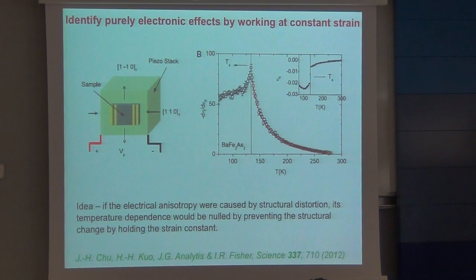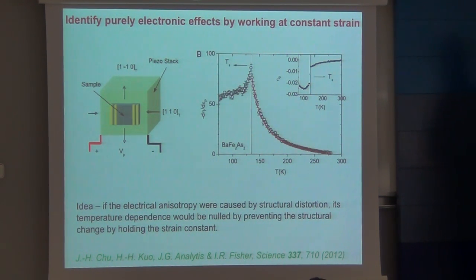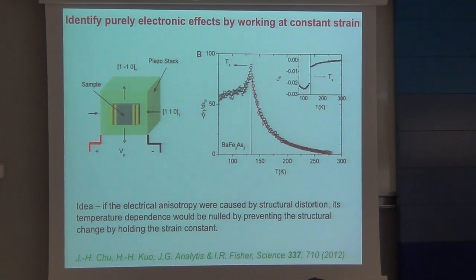And I think once people saw this experiment, they realized that there had to be excellent evidence that there was some form of fundamentally electronically driven anisotropy going on in this crystal. And certainly up at these temperatures, there's no signs of translational symmetry breaking at all. So you imagine this must be some form of electronic nematicity.